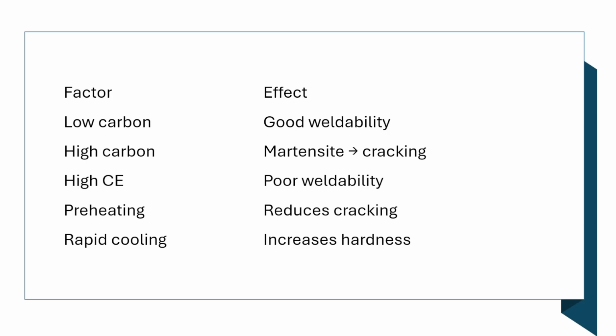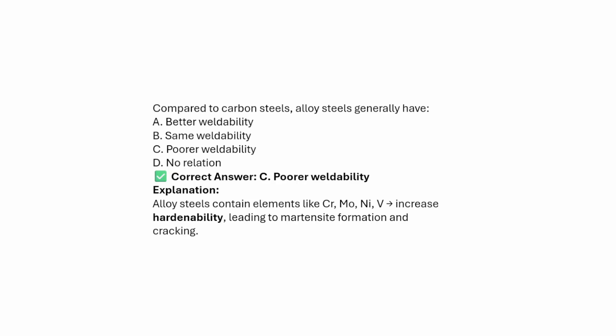So the key points from this lecture are that low carbon means good weldability, and mild steel also has good weldability. High carbon steel means martensitic formation and cracking. High carbon equivalent also means poor weldability. We use preheat treatment to reduce cracking, and rapid cooling increases the hardness. Okay.